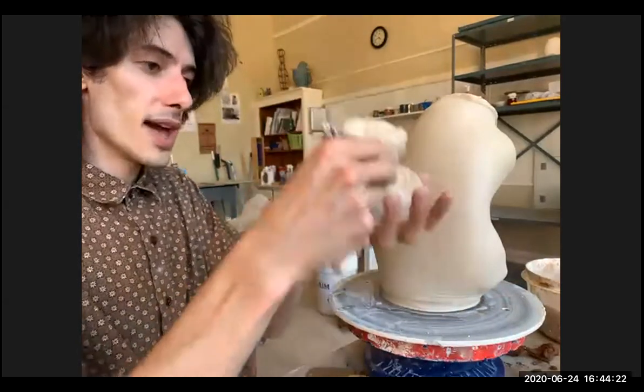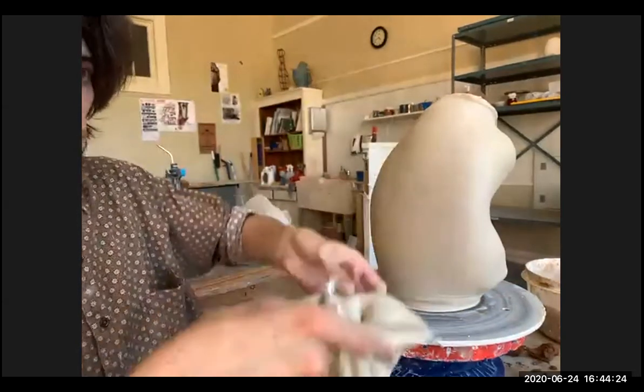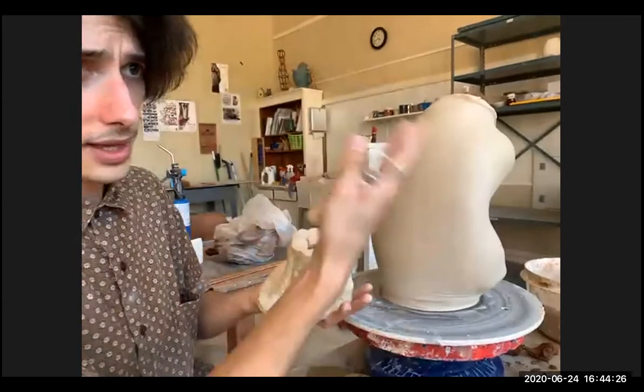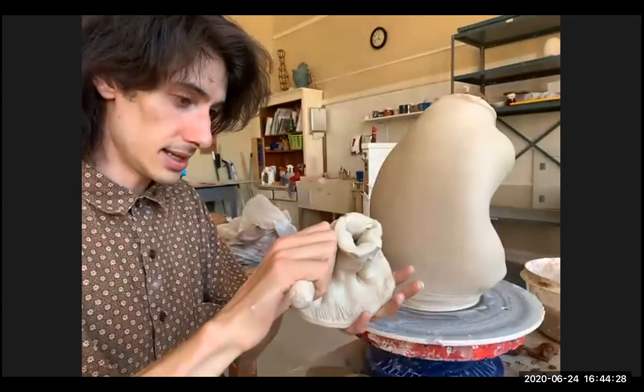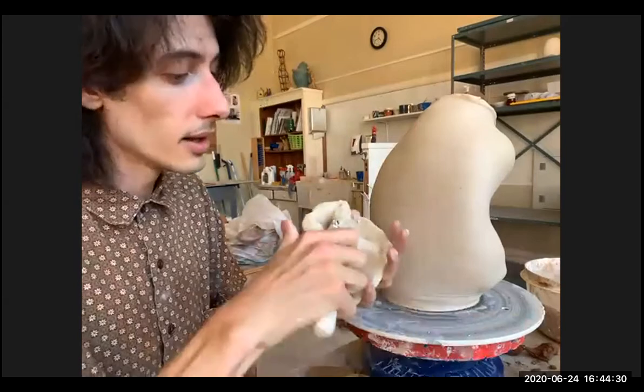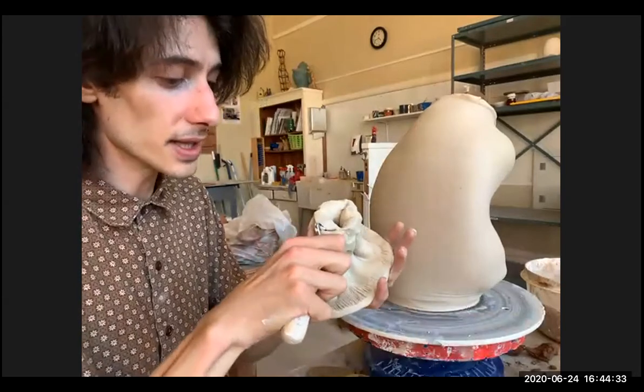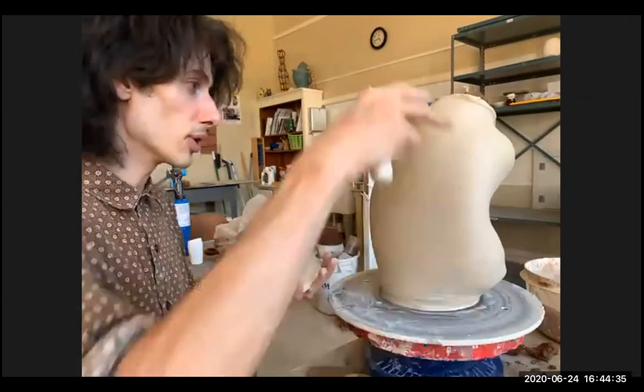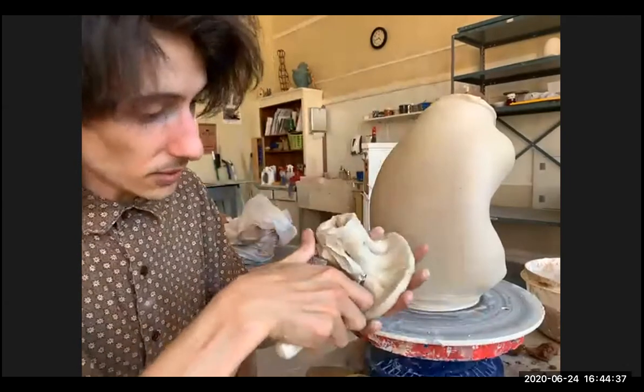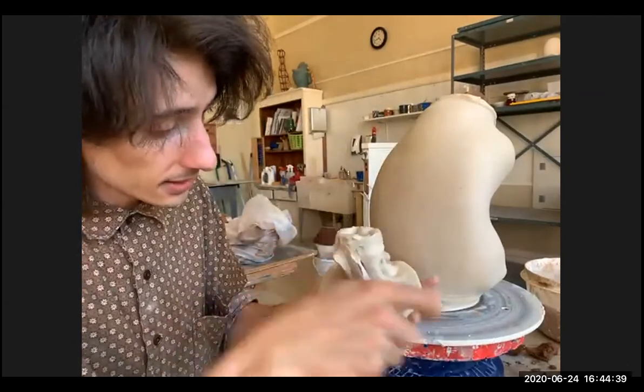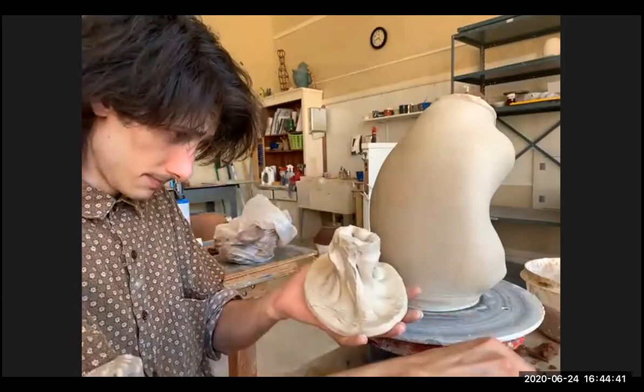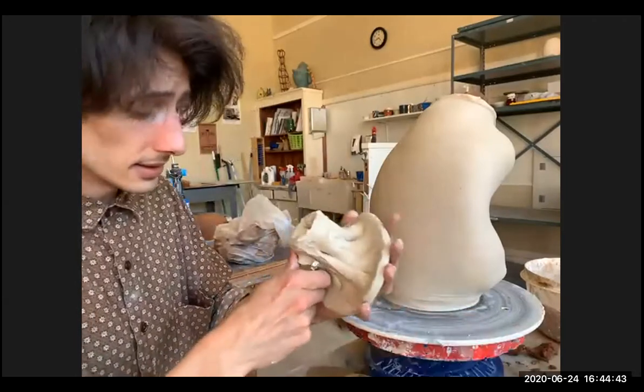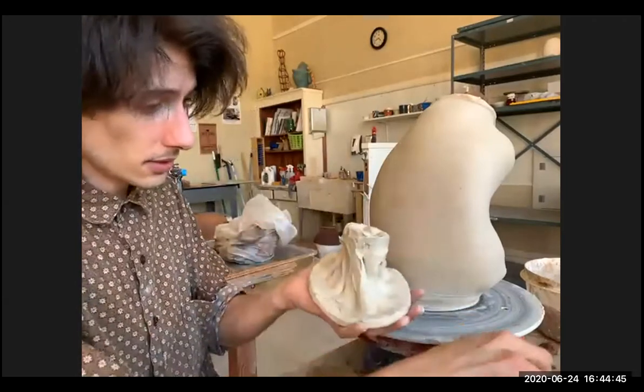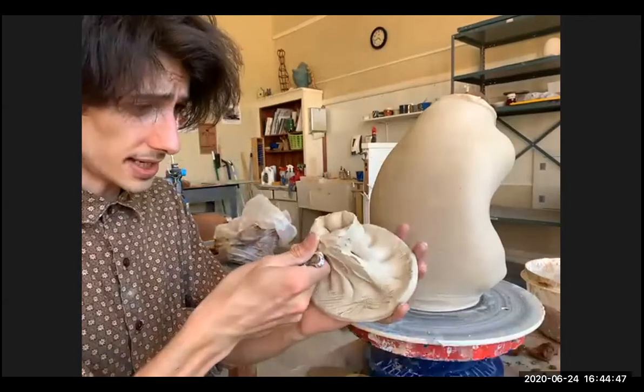If the insert is too heavy, it could even just fall right through the form. It might make this lean forward. You might get cracking issues in the kiln. Like if you put a brick on top of a piece, just the weight when it weakens, when it's fired. Those are some concerns I have.